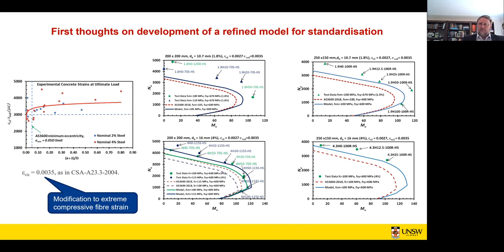So one of the important parameters that we need to think about is the strain in the extreme compression fibre. So in AS3600, you'll know that we use a value of 0.003 for beams that are in bending. And then, of course, depending on what the gradient is, the steel, which may be 60 or 70 millimeters below the surface, will be something less, 0.0025, 0.0026, a value of less than 0.003. Now, 0.0025 is the strain for a 500 grade steel. So we're not getting any additional strength in that compression reinforcement because the model is dictating a strain at the extreme compression fibre of 0.003.